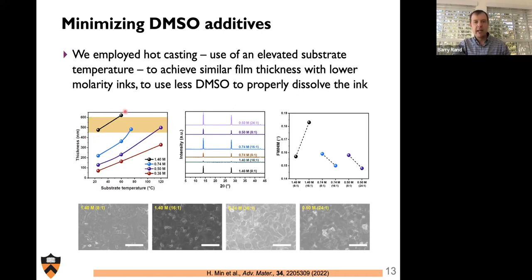And what we see is that obviously higher molarity solutions lead to thicker films for a given substrate temperature, but notably, I can use a 1.4 molar solution all the way to about a half a molar solution and still access films in this sort of thickness of relevance, the 400 to 600 nanometer thick film, where all of my incident photons are nearly entirely absorbed. And I can try to make meaningful comparisons between films of similar thickness and similar quality when looked at from above in an SEM or through X-ray diffraction patterns, which speak to the fact that all films have similar phase state at their starting point. Notably, maybe some of these lower molarity inks even have slightly higher degrees of crystallinity compared to their higher molarity relatives, but I don't think this is anything we need to dive too much into.